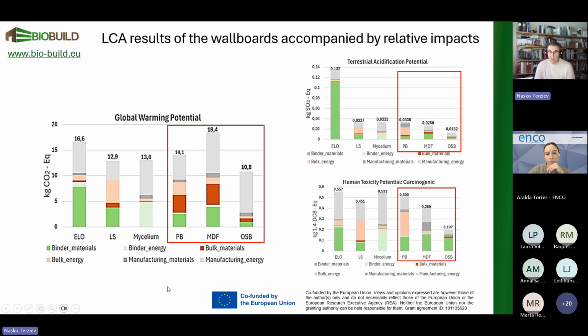I would finish by showing very briefly something that is important and that I'm sure your projects also work with. This is the life cycle analysis of, let's say, our wallboards, accompanied by relative impacts. And as you know, the global warming potential is probably the most popular and frequently used indicator of the effectiveness of the new materials. If you look at the red rectangle, these are traditional materials like particle boards, medium density fiberboard, and oriented strand boards. And these are our materials with the three binders, for example, epoxy oil, lignosulfonate, and mycelium. So I think in our case, we have achieved pretty good results.